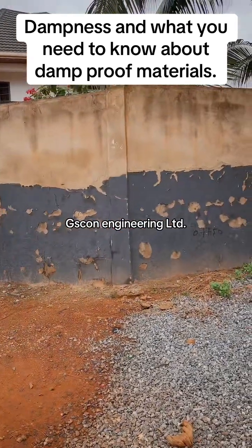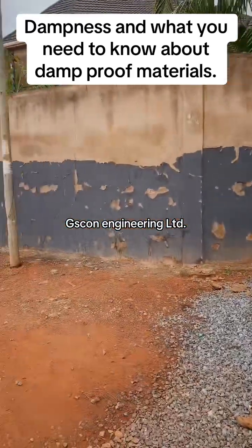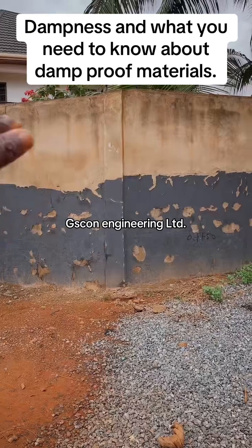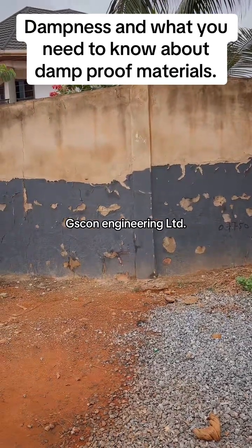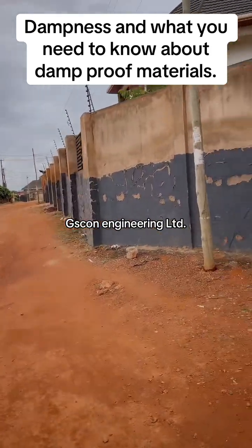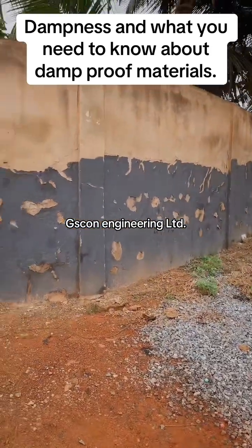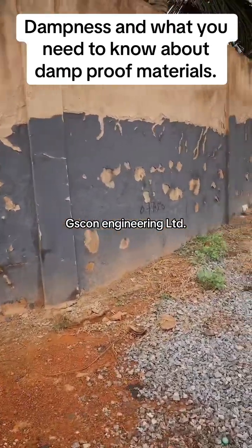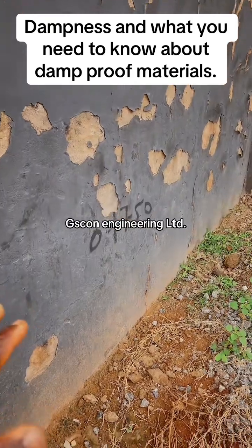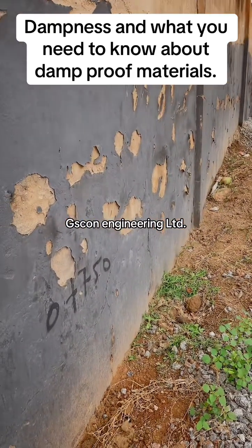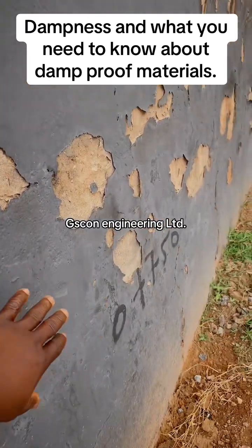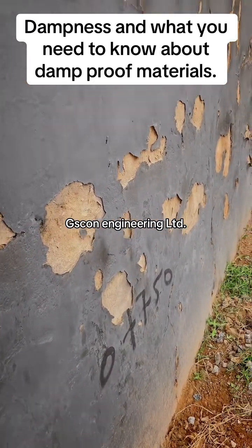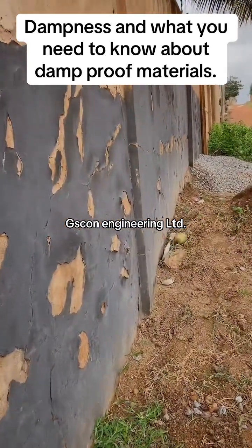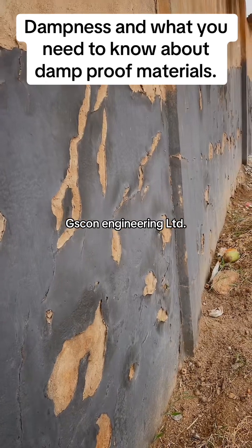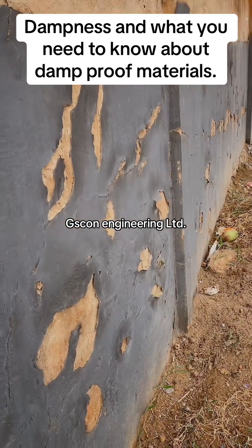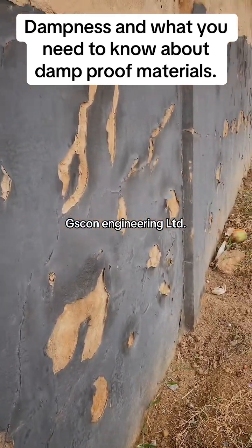The reason being that, why is it that after painting the wall with the damp-proof material, the dampness has risen above it? The thing is that damp walls do evaporate, and some of these damp-proof materials serve as a membrane after painting it, and do not allow the moisture to evaporate into the atmosphere. It traps the moisture in the wall, so the moisture will find its way up to where it can escape from the walls, because when the humidity changes, the air extracts water into the atmosphere from anything that is exposed to air.